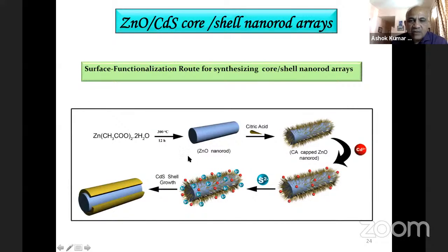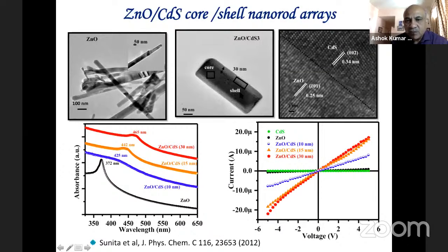This is the synthesis, how we make the zinc oxide, then coat with citric acid, then coat with cadmium ions and use thioacetamide to bring in the sulfide, and then appropriately heat it to get the cadmium sulfide shell structure. These are the TEM pictures to show you that you have the core and you have the shell, and you can vary the thickness by changing the amount of shell material. We have varied it from 10 nanometers to 30 nanometers and measured its optical properties and its current generation capacity.